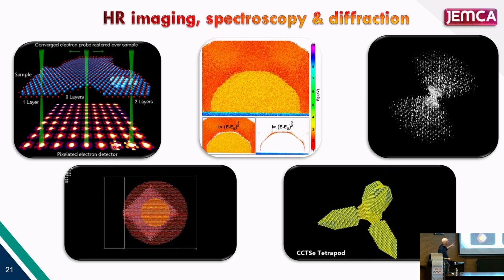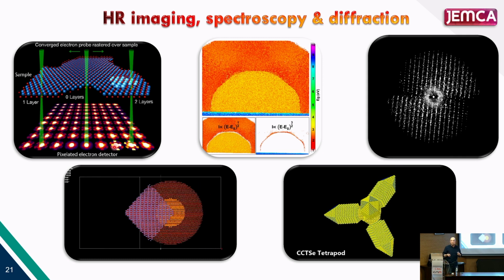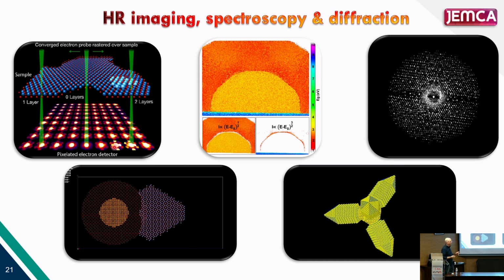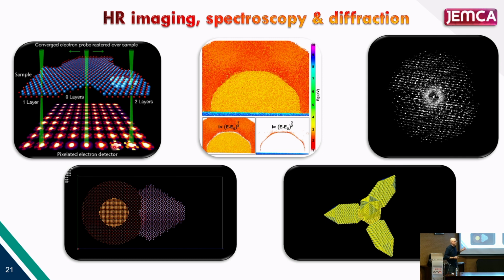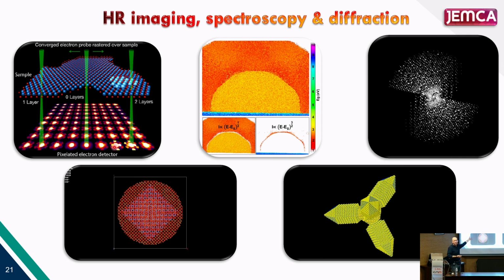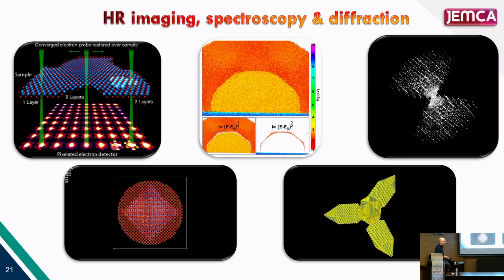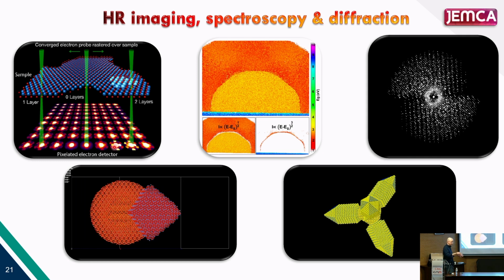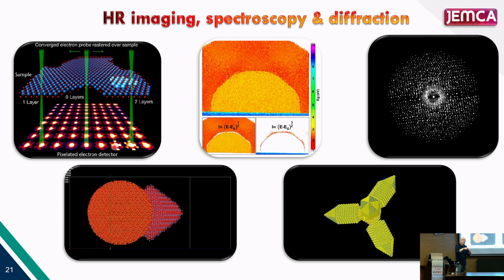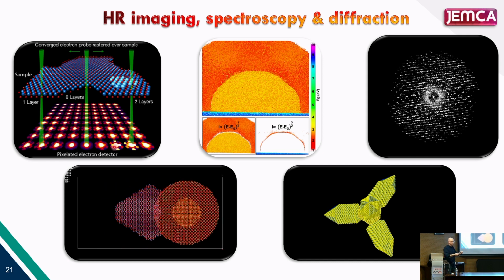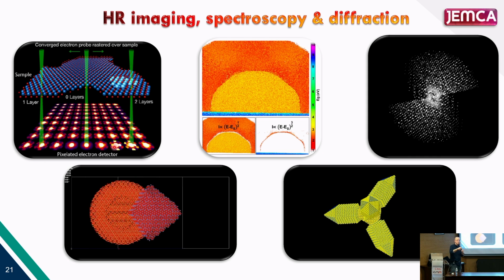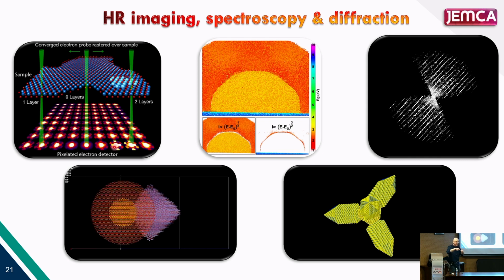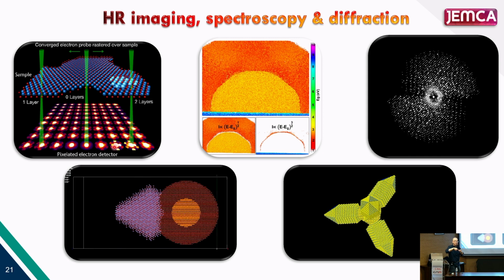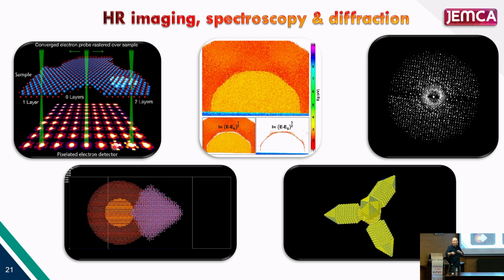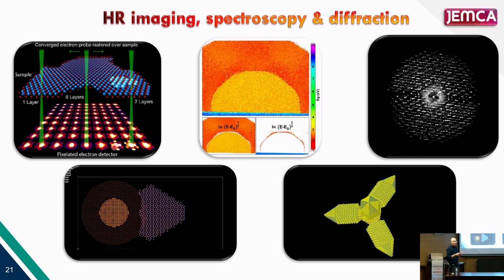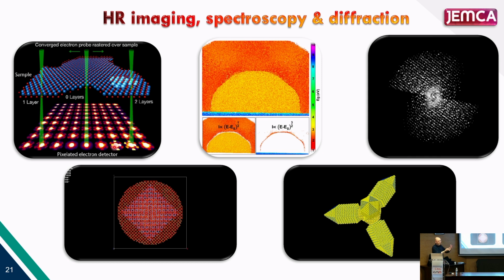It's a really nice technique, not just to improve the resolution of your material, which I think the top resolution right now is 20 picometer in a TEM, like the ones we have, by using this technique. But also you can detect electric fields, magnetic fields, even around atomic columns. For example, if you have gallium nitride, you can see the positive and negative charging field that is around every one of the atoms. The cation and the anion are creating small electric fields, and you can detect that. And you can see it, or you can map it.